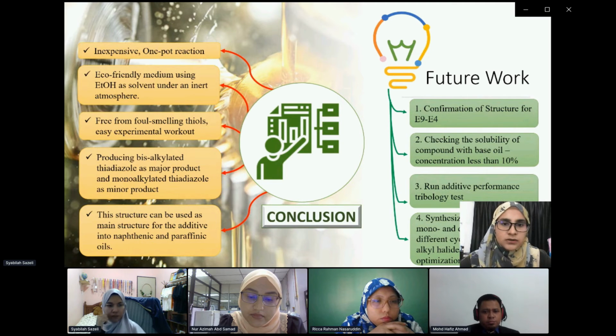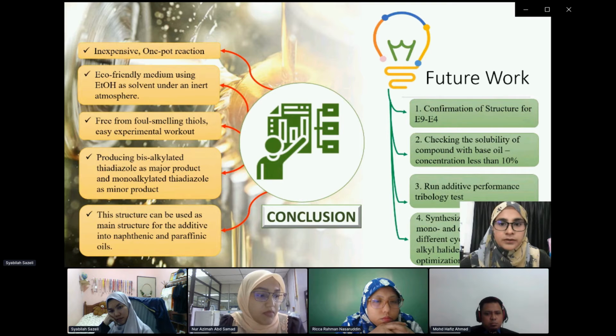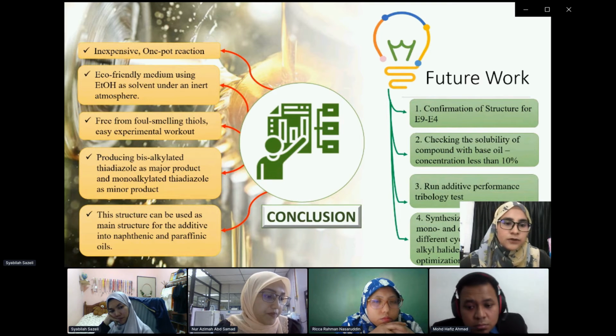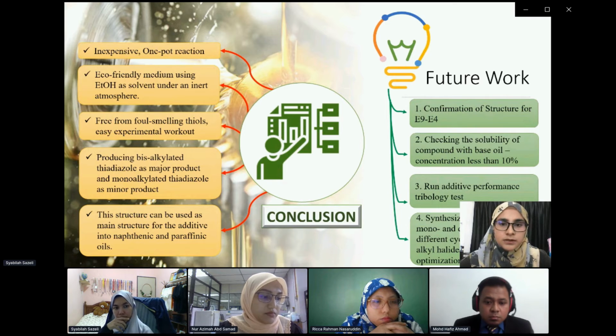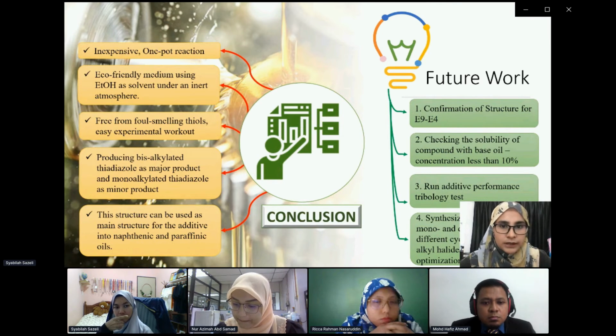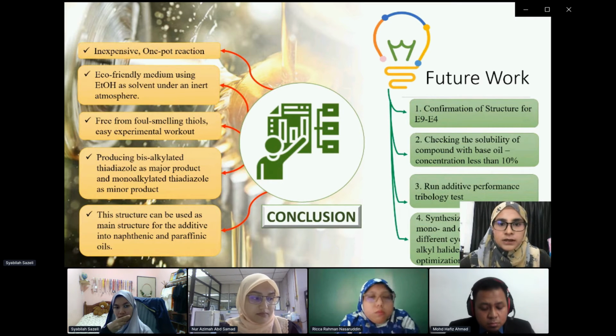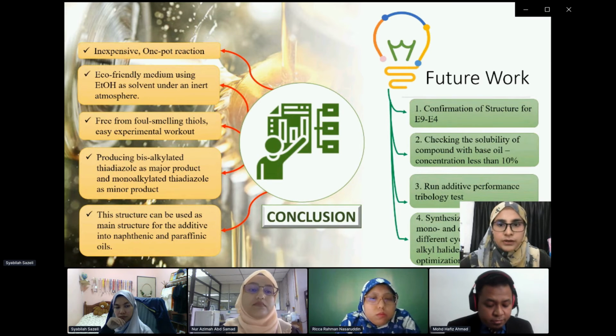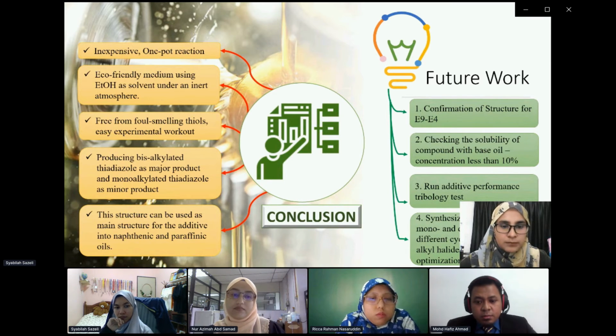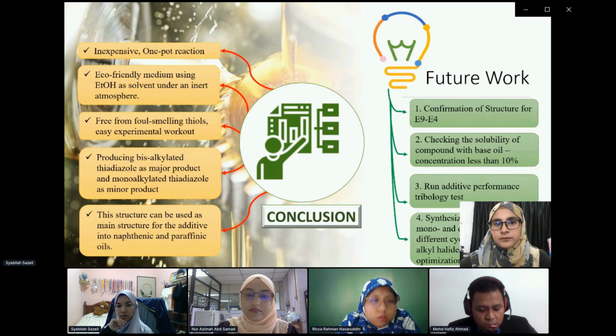Then this reaction is also free from foul-smelling thiols and requires easy experimental workup. Then it is confirmed that this methodology produces bis-alkylated thiadiazole as the major product and monoalkylated thiadiazole as the minor product. So this compound can be used as a main structure for the additive into naphthenic and paraffinic oil.